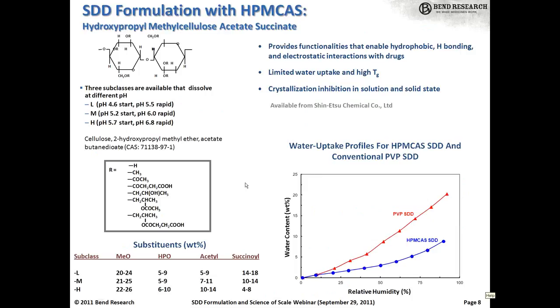As I mentioned, we do use extensively, but not exclusively, the HPMCAS polymer. So this just describes that polymer a little bit and why we use it a lot. HPMCAS is hydroxypropyl methyl cellulose acetate succinate. If you're not familiar with it, the structure is shown here. It is a modified HPMC, basically, if you're more familiar with that polymer. And it is an enteric polymer in that when the succinic acid groups are protonated, it's insoluble. So in the stomach, it's insoluble at low pH. And then at higher pH in the intestinal media, when the succinic acid groups deprotonate, it becomes soluble. It comes in three grades that have different acetate and succinate contents, as shown here, and as such, they dissolve at different pHs.